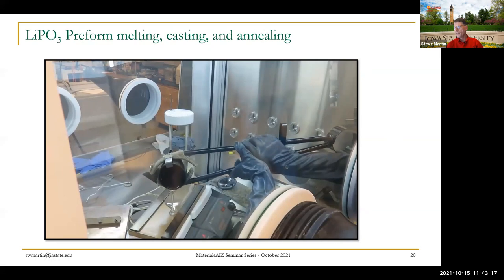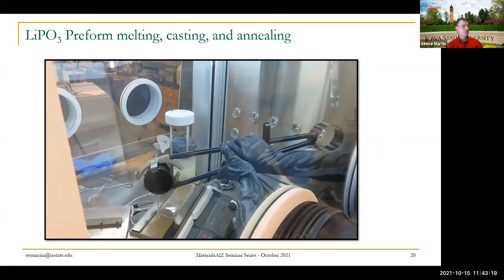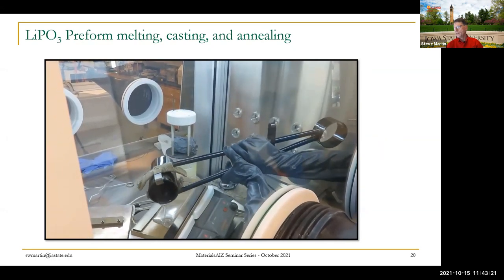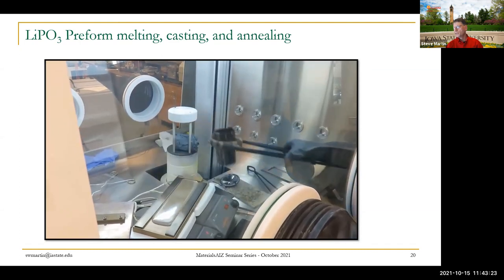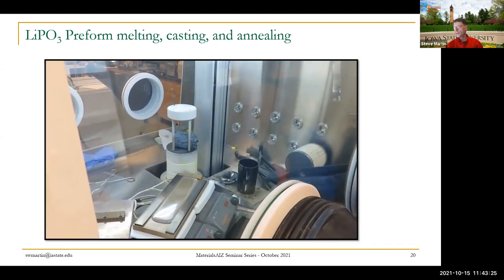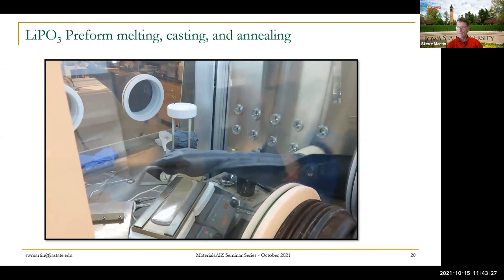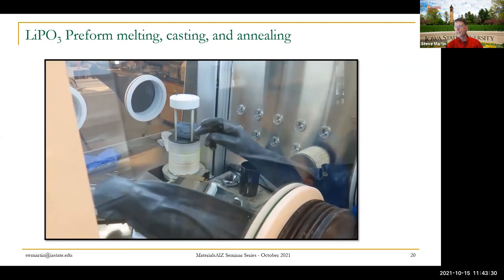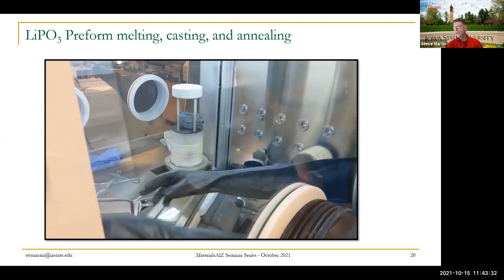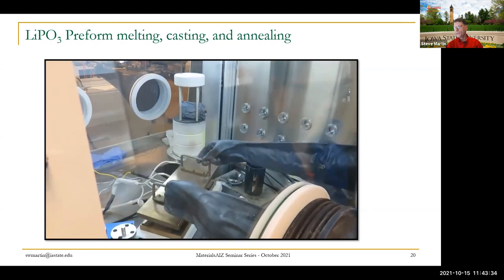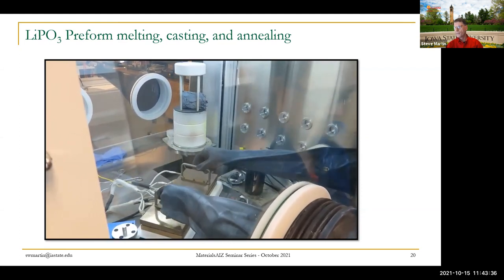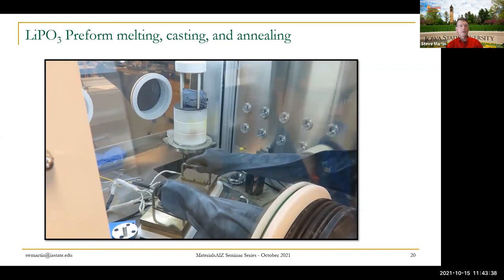And that's the advantage of these glasses that just don't crystallize. They have a large working range, and she just drops it off, and then is going to put the cover on top of it, and that'll anneal that glass. And you can see that we can make preforms that are 10 centimeters wide, about 30 centimeters long, and are amenable to our drawing process.